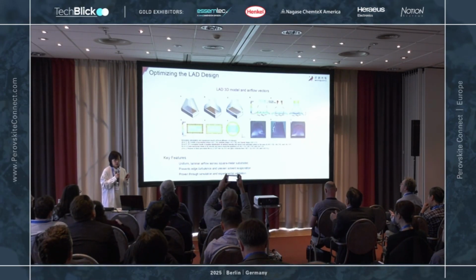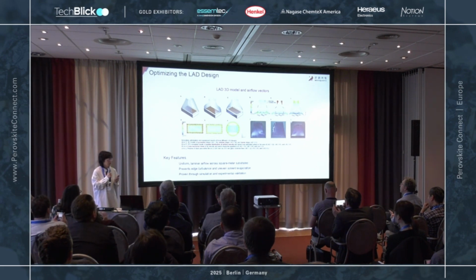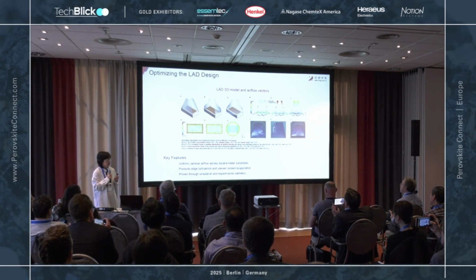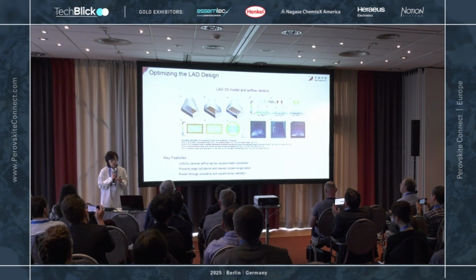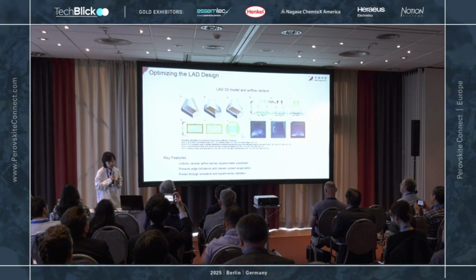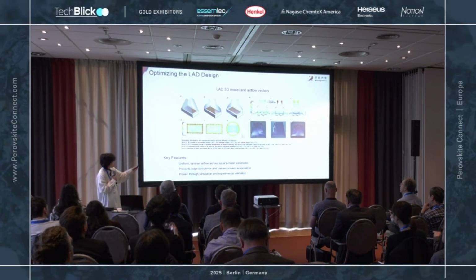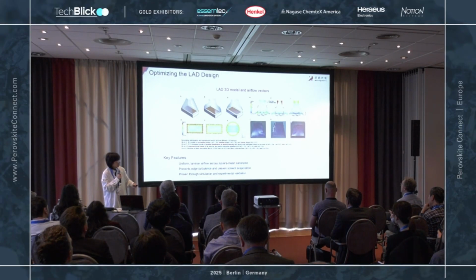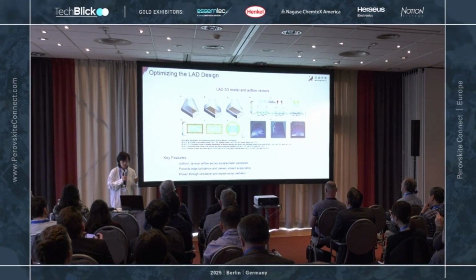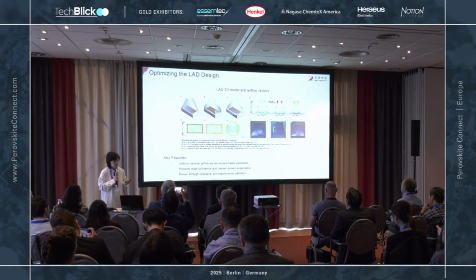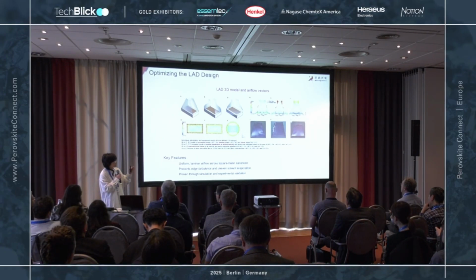We want to get the best result, so we did further work to refine and optimize the design of the light dryer. We finally ended up with this final design on the right. It gives us uniform laminar airflow across the square meter level substrate, and prevents edge turbulence and uneven solvent evaporation. And in the pictures, you can see the quality of this design.